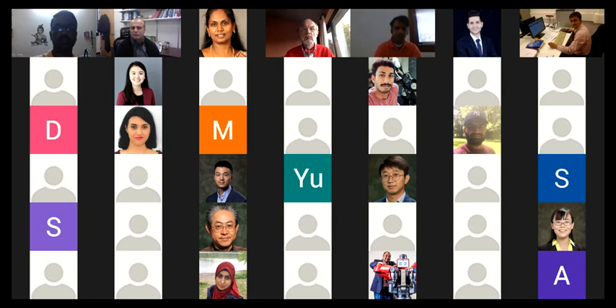So this is Archie Verma from VIT. I wanted to talk about, in general, that when we talk about 3D printing titanium, it usually produces a higher roughness than required by the body implant. So that might not be suitable for a body implant. That requires a lot of post-processing of the 3D printed implant. So I wanted to know if there is any way which we can incorporate during the 3D printing, so that the grinding and the smoothing of the implants will not be required after the 3D printing. Yeah, it's a very good question.